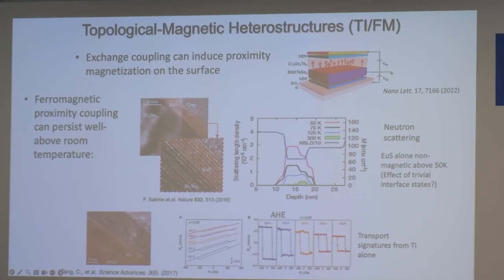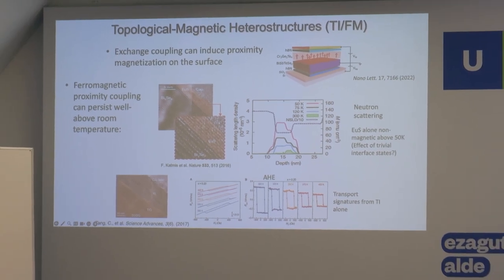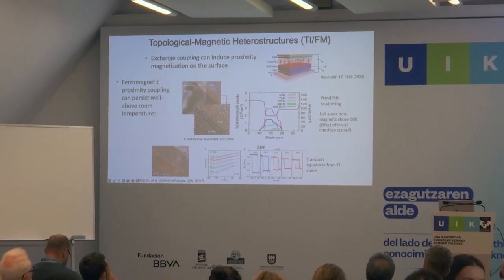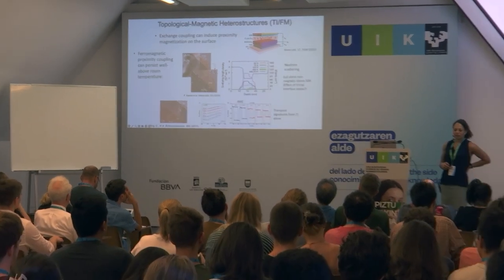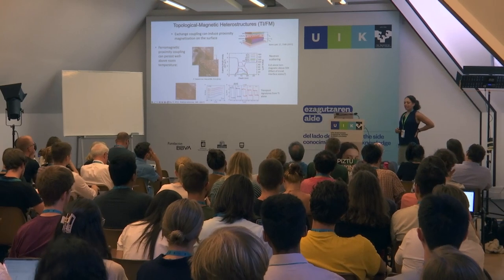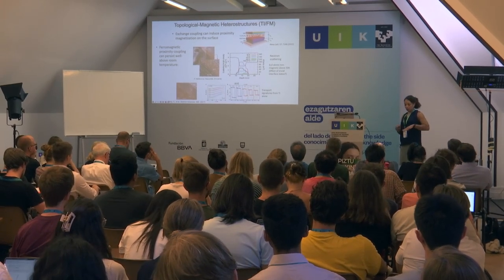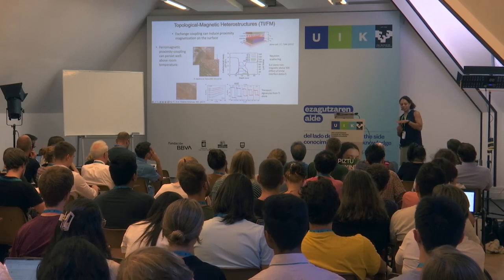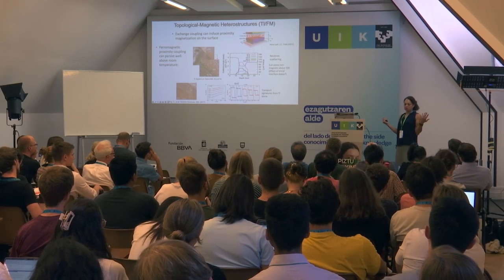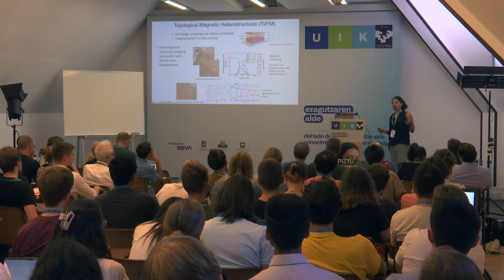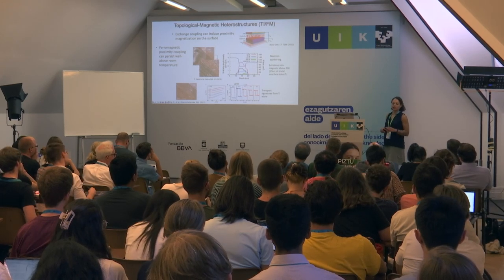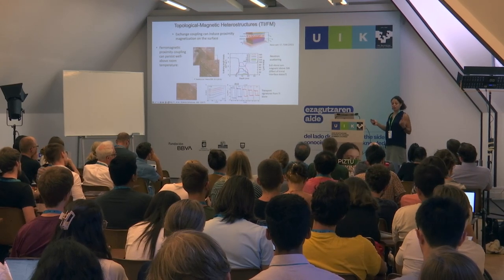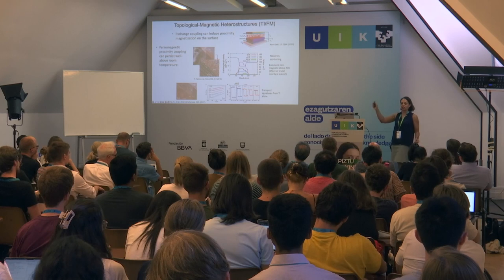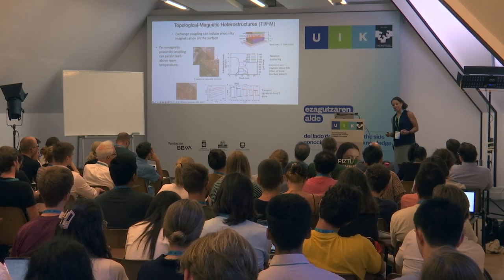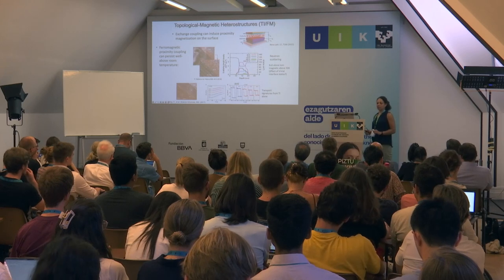Whether this is really exchange coupling or some sort of stray magnetic field penetrating the surface? You get the strongest effects from exchange coupling, yeah. Can you be certain whether it's exchange or stray magnetic field? I can't. So the answer is you can't, but if you don't have a surface at all and put a magnetic field on a TI, you don't see these effects. We haven't gone up to super, super high fields, but if you just go up to 14 Tesla or 15 Tesla, you don't see anomalous Hall effect just by putting a strong magnet. In fact, you just gap out the surface state and you don't see anything interesting in that case. So it does seem to matter that it's exchange, though I can't prove that theoretically.